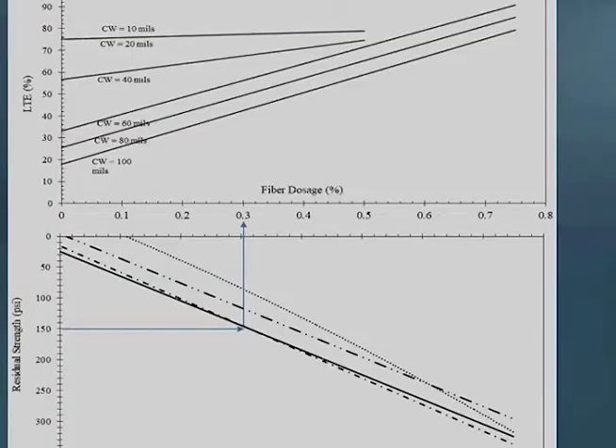So we actually developed this kind of nomograph. In this one you can see, if you know Jeff Roesler's study, they are more focused on residual strength. So for a particular road section you are looking at 175 or 150 residual strength. You can get how much fiber you want to use and what type of fiber. And if Minnesota DOT says, not only that, we also impose a criterion that we want to get this much percentage of load transfer efficiency for that crack width, this kind of nomogram is helpful. So all those results that I am showing here can be helpful in evaluating the contribution of the structural fiber.